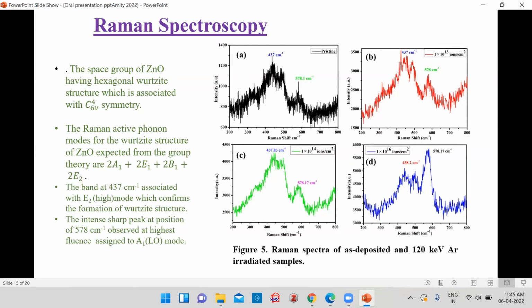With irradiation, all these modes appear in all the images. This gives the stability in the structure of the ZnO. There is also another peak at 578 centimeter inverse. This intense peak becomes sharp with increasing irradiation. It is assigned to the A1 LO mode.